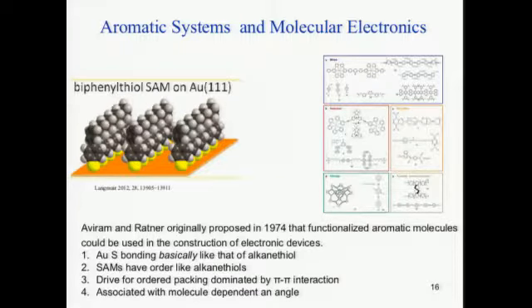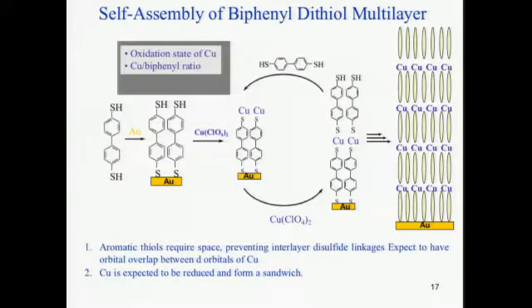But what they do have in common is the gold-S bond that's formed, and that there is order when you make a monolayer. Unlike the alkane thiols where you have van der Waals interactions, in this case you're looking at pi-pi interactions of the benzene, and there's a known angle associated with the molecule. So I went out to look at how I could use molecules like biphenyl dithiol to make a multilayer in this way.